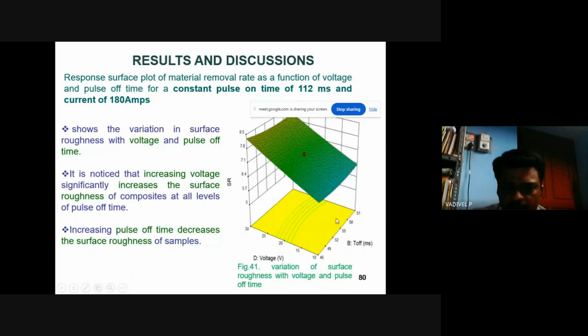And this is the plot of the variation of surface roughness with the voltage and pulse off time. Here it is noticed that increasing the voltage increases the surface roughness of the composite at all levels of pulse off time, while increasing the pulse off time decreases the surface roughness of the samples.